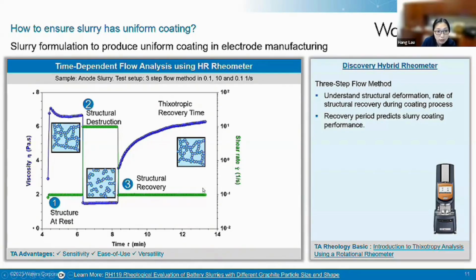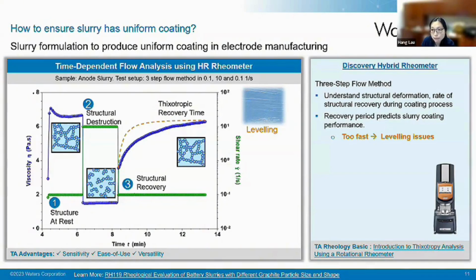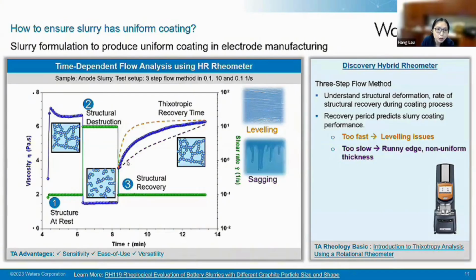There's a few things very important to test, such as whether your recovery time is too fast. Imagine you're putting paint on the wall. If the recovery time is really fast, you will see the brush marks. It's the same way with the coating machine. Once you're coating, it may have a defect that may not level out. You may have an uneven coating with what we call a leveling issue. And if it's recovering too slowly, it may take too long, and you may have a runny edge or sagging, similar with the coating.